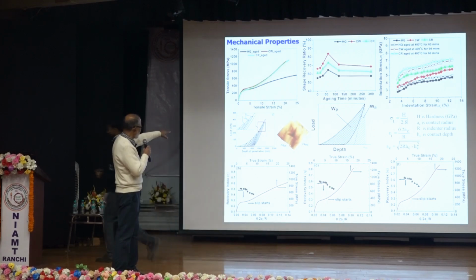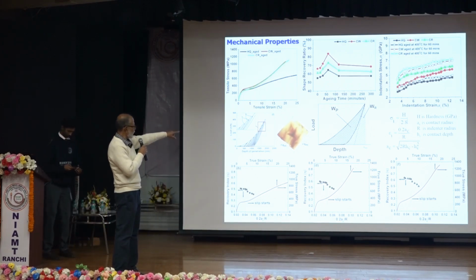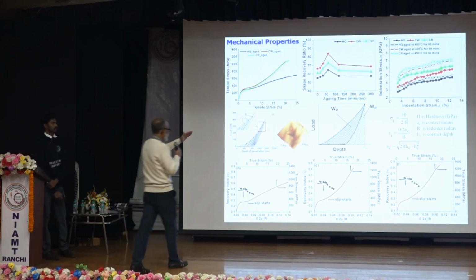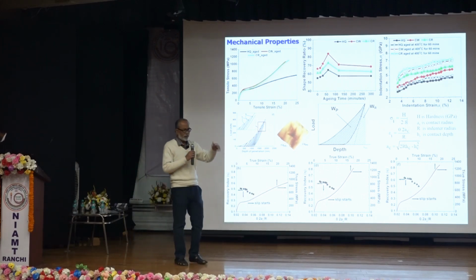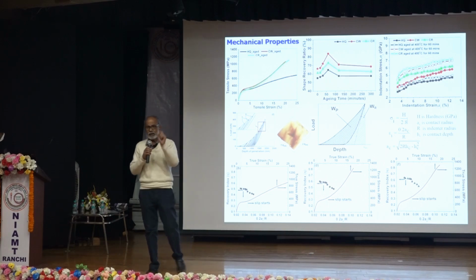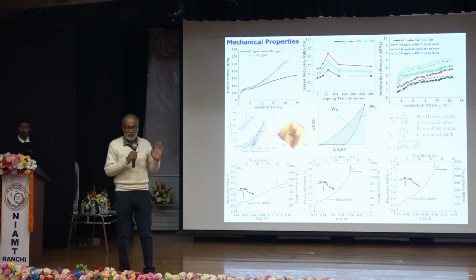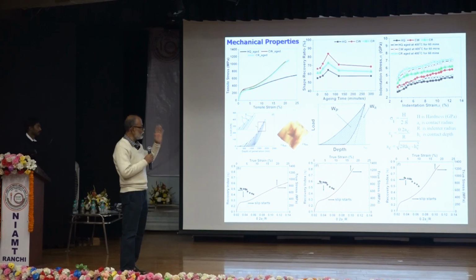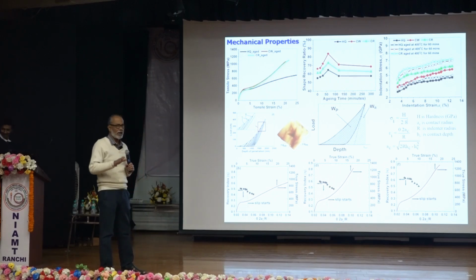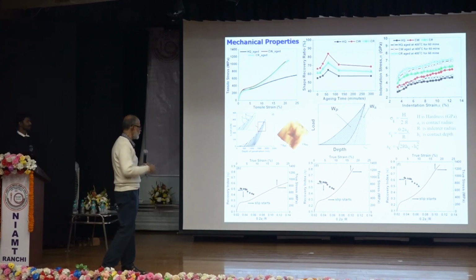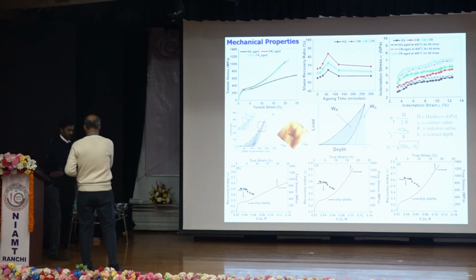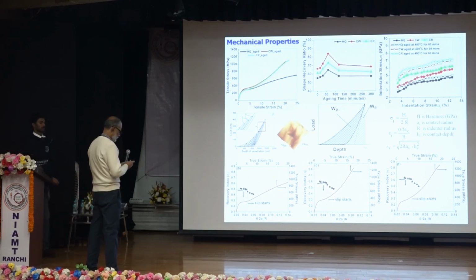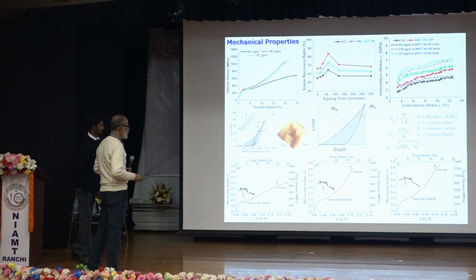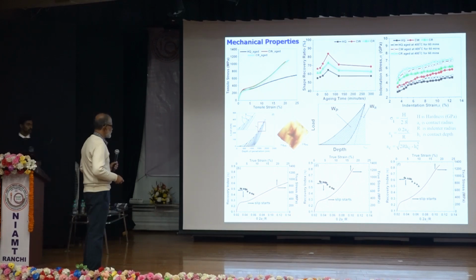This particular diagram exemplifies the hardening mechanism, and moreover, we conducted an AFM experiment where we found a sink-in effect. In hardness measurement, when there is a sink-in, it infers strain hardening. So strain hardening was confirmed in NiTi, and we were expecting the CRSS to increase by that, but we didn't gain anything in terms of shape recovery or strain behavior.